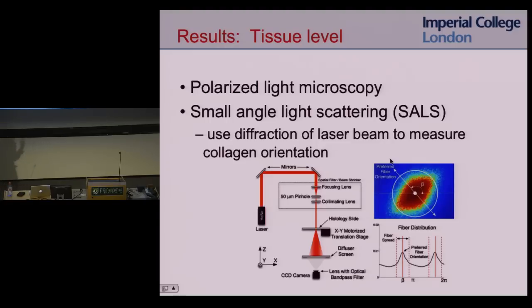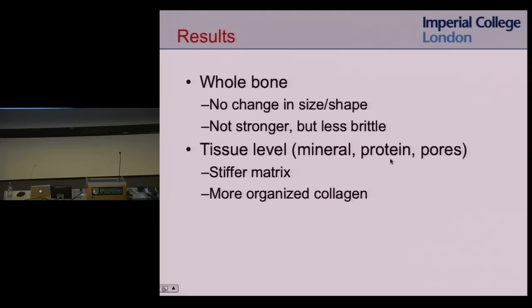So this is ongoing work. The optics are proving challenging because we need a spot size of about 1 micron to get sufficient resolution to be able to measure anything. So we're still working on it. But it seems from our polarized light microscopy that the stem cell treatment makes the collagen more organized.